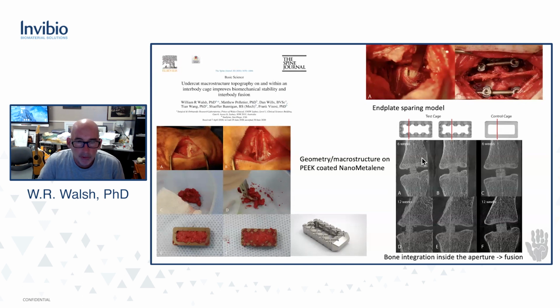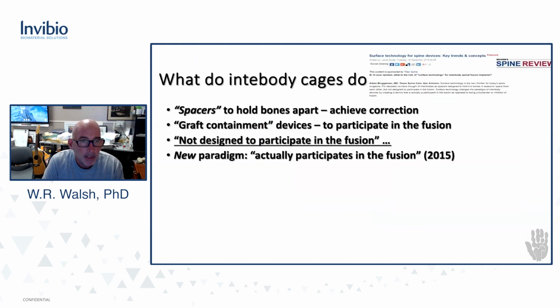And just to illustrate that the geometry drives the fixation and then ultimately facilitates the interbody fusion in the aperture. So the little interstices or the macro topography features can get captured. But we can see everything here because the NanoMetalene is not visible even on micro CT because it's such a thin coating on PEEK Optima.